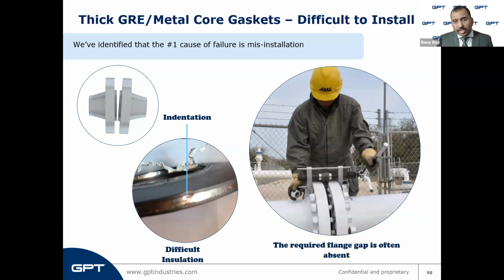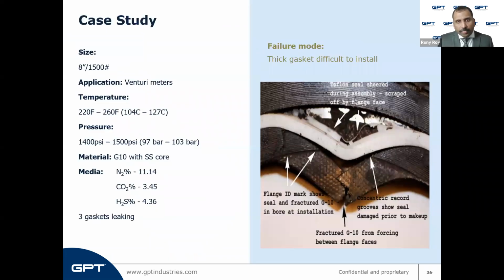So the common 6.6 mm thick isolation gaskets will be a difficulty to install in pipelines that are designed for gaskets that are 3.25 mm thick. Flanges that are not perfectly parallel and are not well aligned will present even greater issues. A case study about how this can go wrong is here. This is a live example of bad installation. 3 isolation gaskets were installed in the upstream side of a venturi meter. Not enough flange gap was created and the isolation gaskets were damaged during installation.